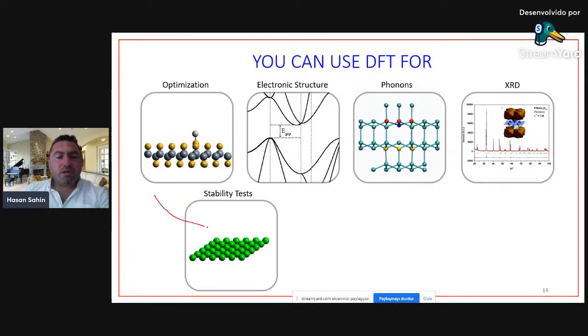And another type of stability test. Here I'm imagining a single layer of chlorine atoms, and I'm increasing the temperature. What is the effect of temperature on this structure? As you see here, atoms are a bit distorted in time as the temperature increases. As you notice now, it's all ruined. So this calculation says that there is no stable single layer of chlorine, it will be destroyed at very low temperatures. You can examine the stability of your system against increasing temperature. It's possible.